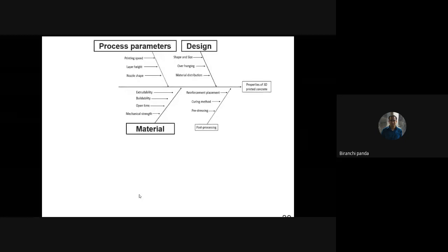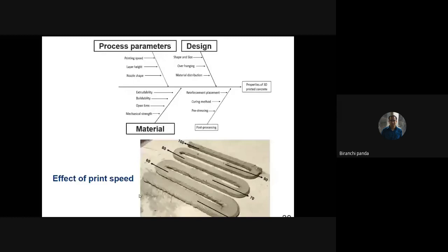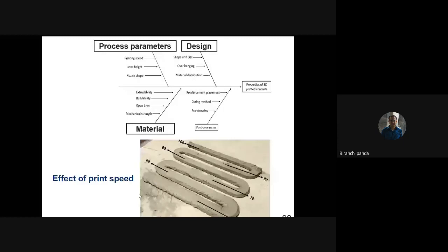If you see, we have been printing this material with different printing speeds, keeping the flow rate constant. When the flow rate is constant and you change the printing speed, you will find an optimum printing speed at which the layer width and dimensions will be similar to your nozzle dimension. We count that as the optimum speed, because for other speeds, either there will be over deposition of material or less deposition of material. So we conducted different printing speed experiments, keeping the flow rate constant, and tried to identify for different materials the optimum printing speed so that the layers will not be deformed, and there will be no extra or less material in the filament. As you can see, printing parameters also have some impact on the filament property.